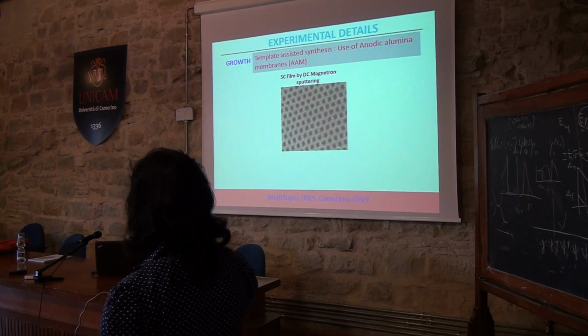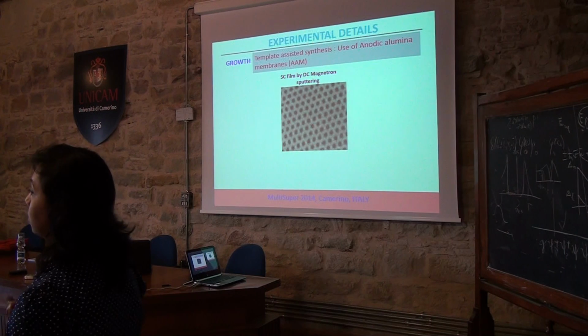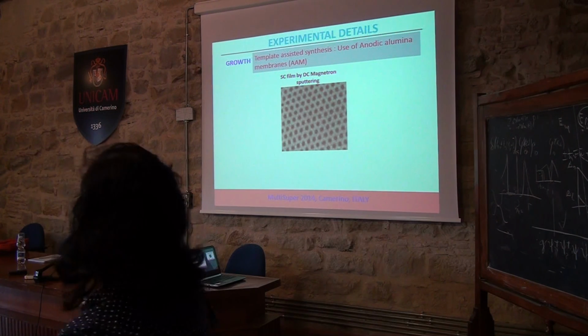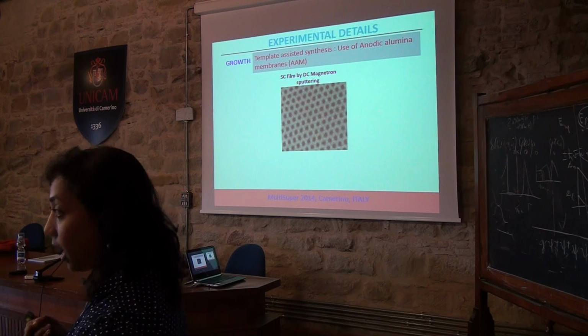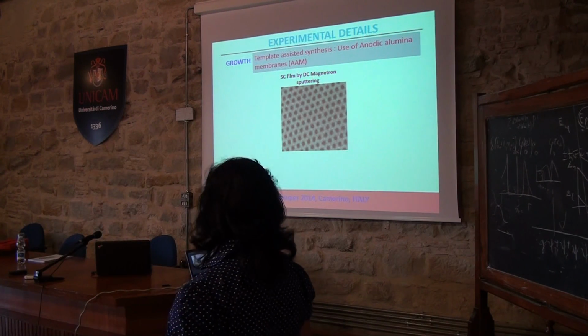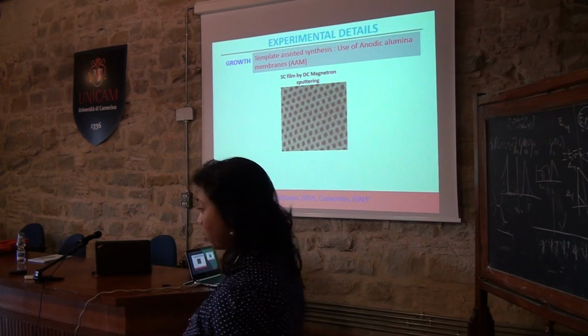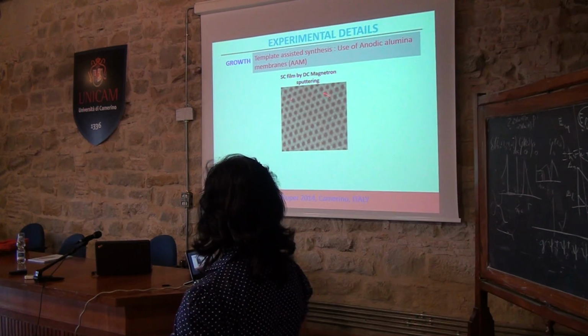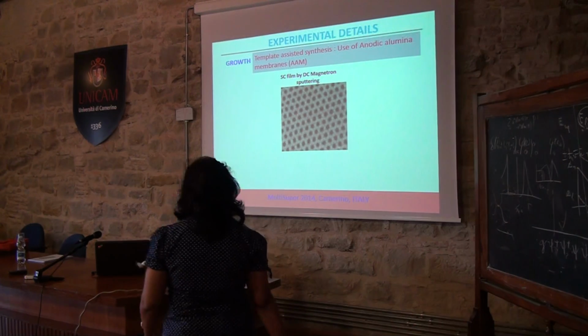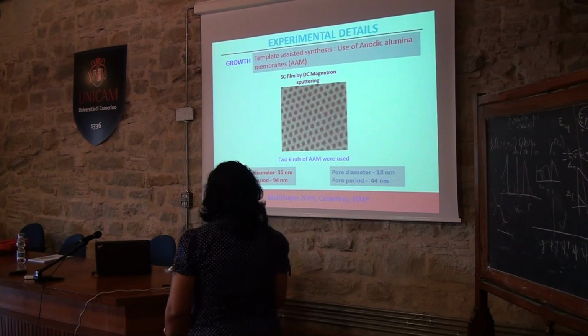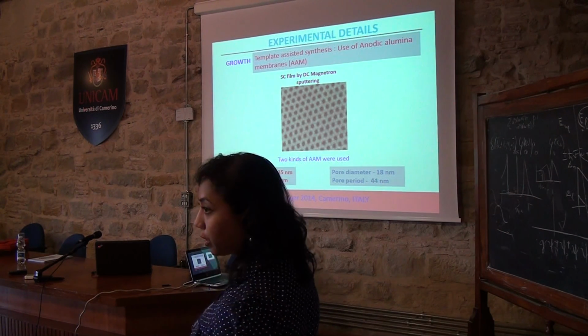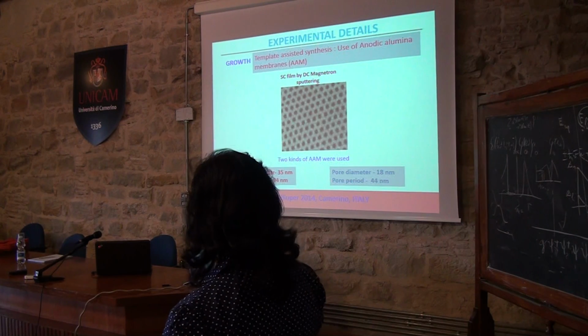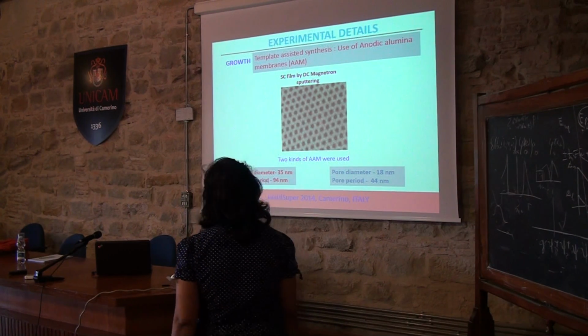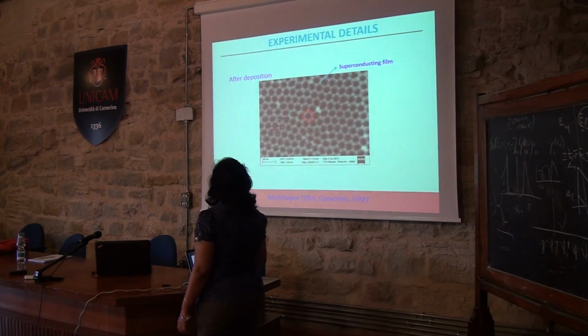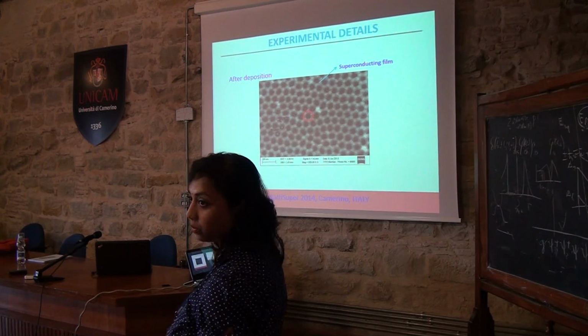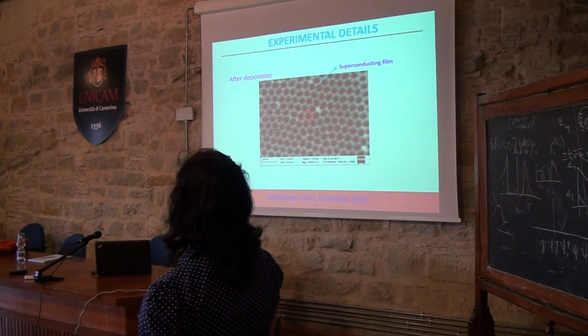So a little bit on the samples. The samples were synthesized using predefined templates. The template was nothing but a membrane of aluminium oxide, and in these templates you had predefined pores which were perfectly ordered in a hexagonal arrangement. We used templates of different pore diameters, one in which the pore diameter was 35 nanometer and the other in which it was 18 nanometer, and consequently the pore period was also different in the two cases. And on top of that, we deposited a superconducting niobium nitride.